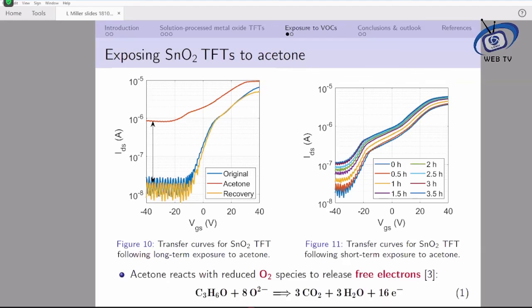And this was attributed to free electrons within the tin oxide film that were released following a redox reaction between acetone and the oxygen species adsorbed to the surface when the thin film transistor was left in ambient after fabrication. Following exposure, the device was placed on a hot plate at 100 degrees Celsius for 1 hour, and electrical performance was recovered successfully, as the transfer characteristics before exposure and after heating were well matched.